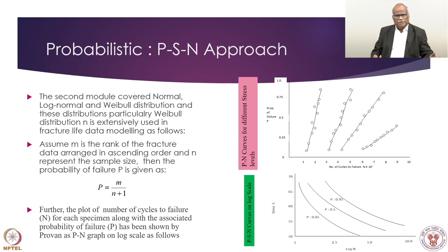We have a very efficient approach called the PSN approach. In the PSN approach, we have the stress reversals against the number of cycles. These correlations are plotted, and finally what we get is the PN curve, the probability here and number of cycles here. So we get these curves for various samples, and finally we convert them into PSN curves, probability, stress, and number of cycles, and have the confidence bounds at 5% and 95% and so on. But then what is the approach for estimating the probability of failure?